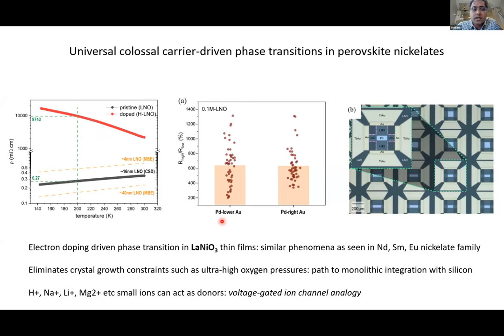And so this is actually interesting and important for practical applications. And the reason for that is some of the rare earths require supremely high oxygen pressures. So our early work 10, 12 years back when we started working on this, we were using ultra high pressures to synthesize the samarium nickelates. And then slowly we transitioned to neodymium nickelate because you don't need super high pressures. And then more recently, we are exploring lanthanum nickelate. So basically the choice of material opens up the ease of deposition techniques, and becomes a little less constrained.